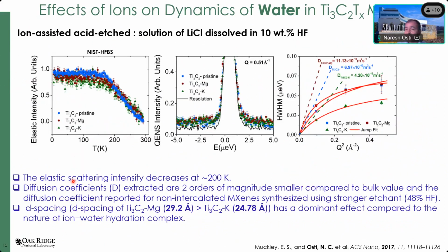Now I'm moving to a different type of MXene, which is synthesized using lithium chloride dissolved in 10% hydrofluoric acid, but we are still looking at the water dynamics. Here I have the elastic intensity profile as a function of temperature for the pristine MXene, the magnesium intercalated MXene and the potassium intercalated MXene. The scattering patterns look almost similar, but there is no step in the elastic intensity profile, indicating that the water is much more confined in this system.